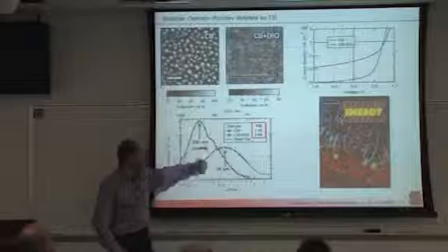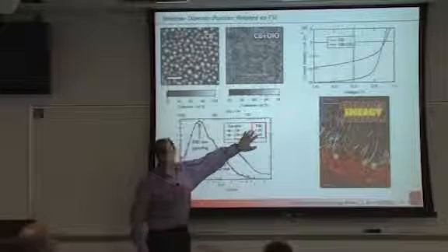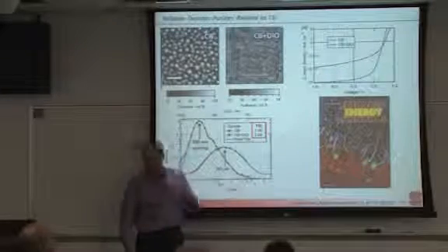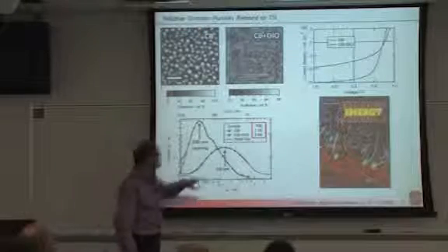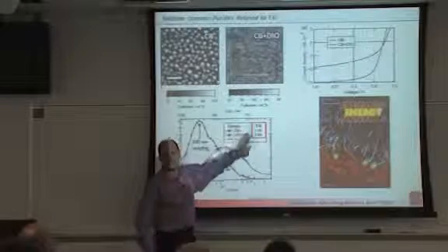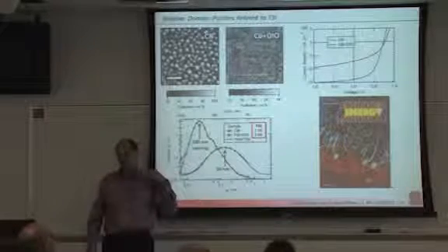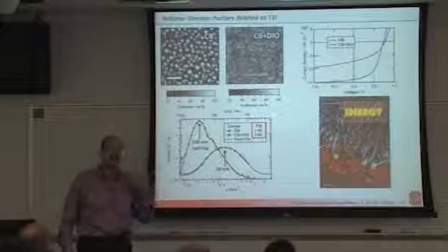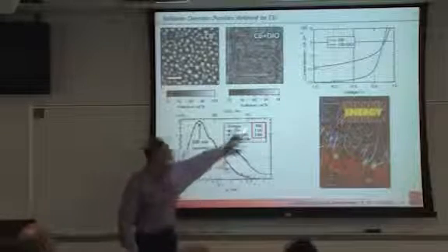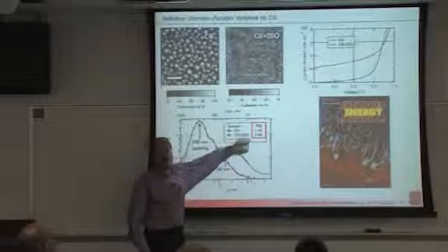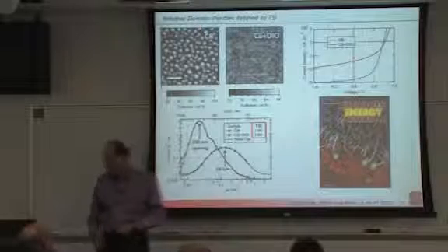We integrate the scattering intensity, and that is different by 10%, but the composition fluctuation is the square root of that. So within 5%, essentially, the composition fluctuations, and therefore the relative domain purities, are the same in these materials. And that is something that you can pull out from the scattering that you wouldn't know otherwise.